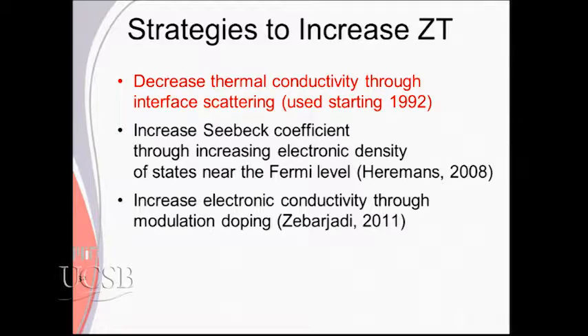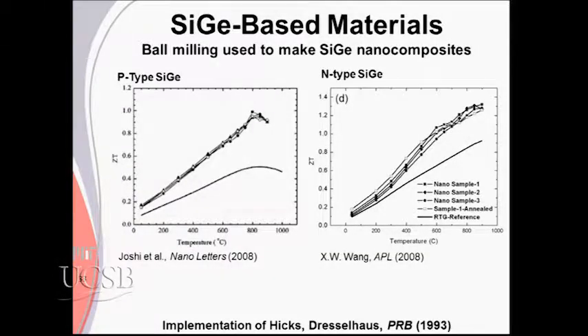So the first idea is introduce more scattering centers. Well, you can make the system more nano. You can put in little metal particles. I learned here visiting today that's a good way to do this. We didn't do this, but that could be done. So any kind of idea to reduce thermal conductivity is good. And so you have to do it with N and P type components because the device always has N and P type. So if it works for one kind of type and not the other, you haven't really solved your problem yet.